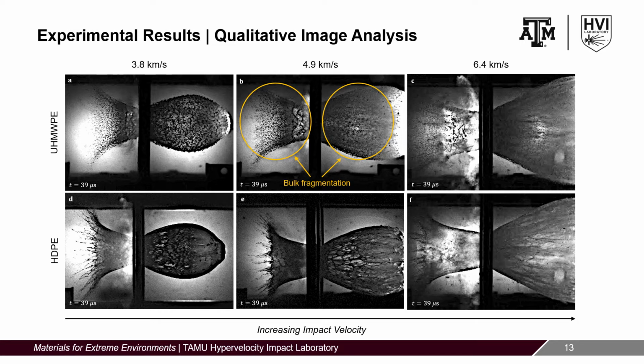In addition to fragmentation, a small region of the front face debris cloud near the impact surface shows signs of minor melting. In contrast, high-density polyethylene exhibits little to no fragmentation. Instead, the front face and back face debris clouds for high-density polyethylene exhibit apparent bulk melting over the velocity regime tested. For both materials, the average front face and back face debris cloud sizes increase with velocity.